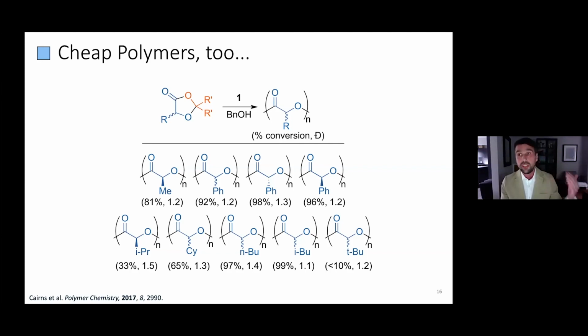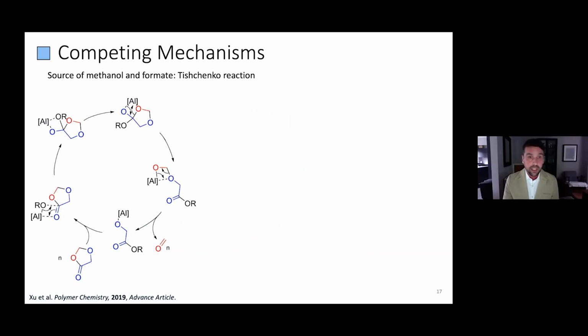And it's one of the reasons why we focus on the formaldehyde system, is because the polymerization is easier at those lower temperatures in the system. So I mentioned before that we do a lot of catalytic mechanistic work. So these aluminium-based systems, if we start down at the bottom here, I take my monomer, I do a coordination of that, and I'm starting from an aluminium alkoxide, and I basically have a attack at that ring. Acyl bond cleavage, which is the cornerstone of ring opening polymerization, however, is more complicated here. Because I have an ester acetal, I end up with this really unique functionality here.